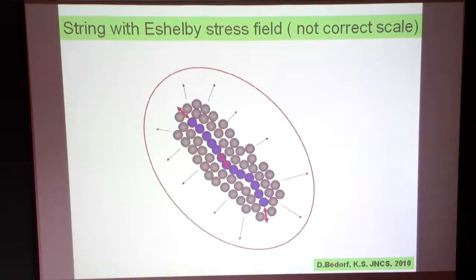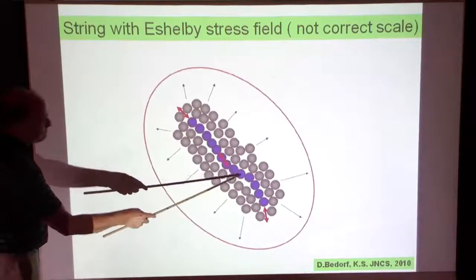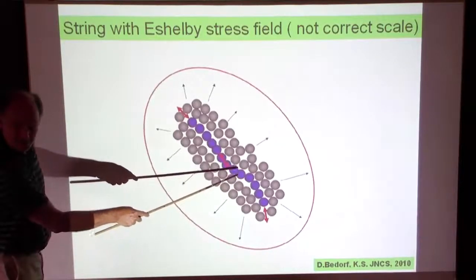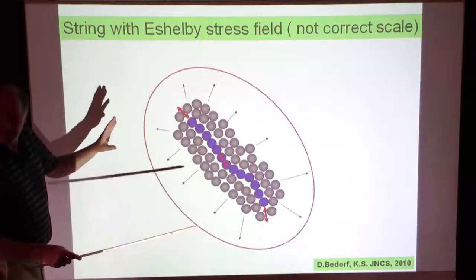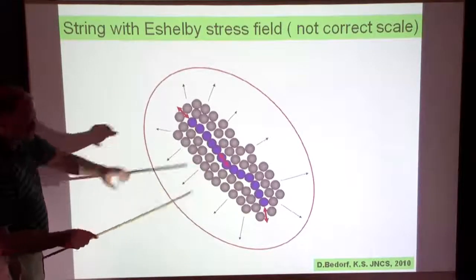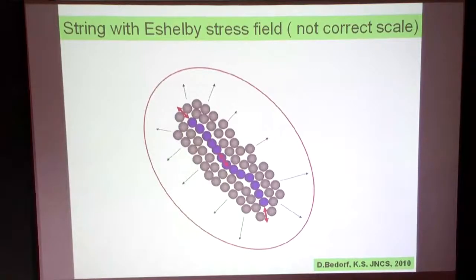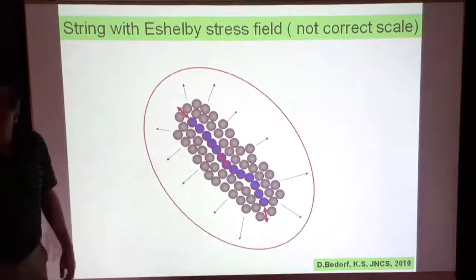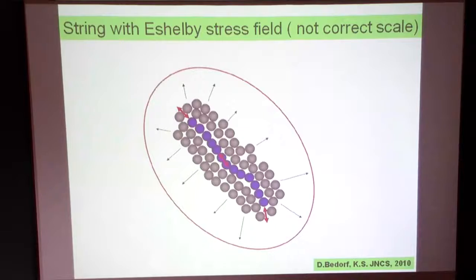position. And so if you fix, for example, what we did with Itamar, fixing one of these atoms, pin it down in the MD simulation, and the whole beta process gets killed by 2%. So you pin only one of these atoms in a string, and its whole is stopped. But I guess your question is about strings of arbitrary length? No, the length scale here in the MD system is about 20 atoms. We talked about that in colloidal systems. There might be only a couple of atoms, actually, the strings. It depends from system to system.